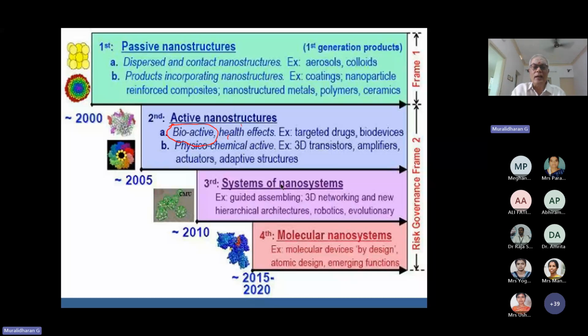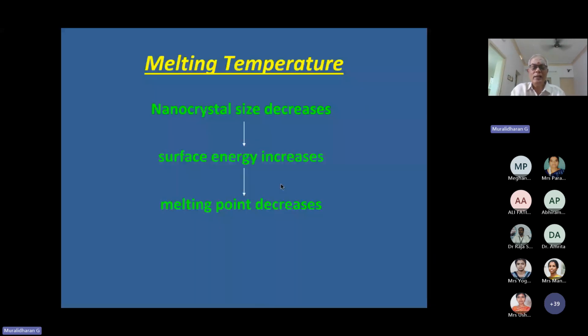So let's look at a case where the material has been shredded into nano dimensions, and what really happens to the melting point. You see that when you make cadmium selenide, if it is bulk cadmium selenide, when I say bulk, it can be a millimeter by millimeter, it melts only at 1678 Kelvin, or say about 1400 degrees centigrade. And the moment you make it into a 3 nanometer cadmium selenide crystal, it melts at 400 degrees centigrade.